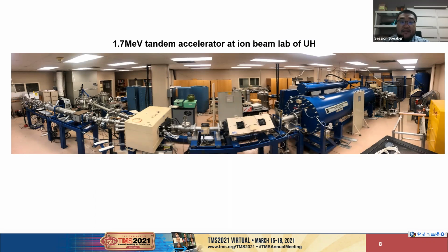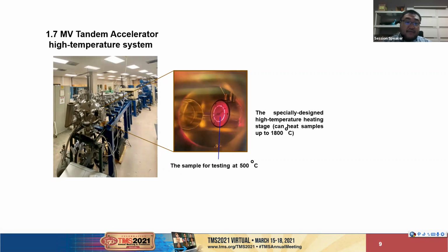This shows the overview of the 1.7 MV tandem accelerator at the ion beam lab of the University of Houston. You can see that this tandem accelerator is able to generate most elements and isotopes, covering energies from a few tens of keV to over 10 MeV. And this is the side view of the tandem accelerator. Specifically, we have a specially designed high temperature heating stage, which can heat up the sample to 1800 C, which is very high. The purpose of such high temperature is to simulate the harsh environment in advanced nuclear reactor concepts.